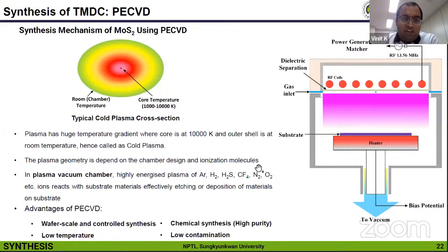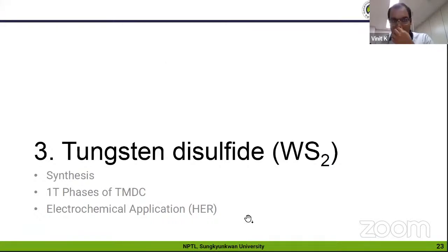So what is the advantage of our PECVD? We can go for very large scale synthesis, wafer scale synthesis. Also, we can make this controlled synthesis at low temperature. We can achieve high chemical purity, and due to the low vacuum and no typical solid reaction happening, there is low contamination in this case. So we utilize this PECVD condition for synthesizing tungsten disulfide.